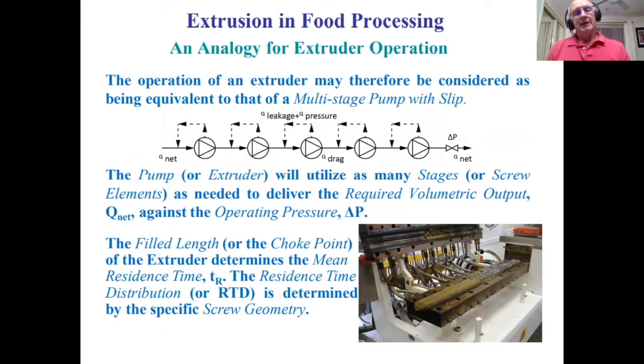In simple terms, another analogy that you can use to understand an extrusion system is that every screw element within the extruder geometry acts like a pump with slip. And so an extruder is simply a multi-stage pump with slip. The magnitude of that slip depends on the local viscosity, the local pressure, and the local geometry. So by changing the screw geometry, we change the balance between forward and reverse flow components to influence the transformation of the product, or the cooking process itself. And so the extruder will backfill or utilize as many stages of the screw elements as is needed to deliver the required volumetric throughput against the current operating pressure.